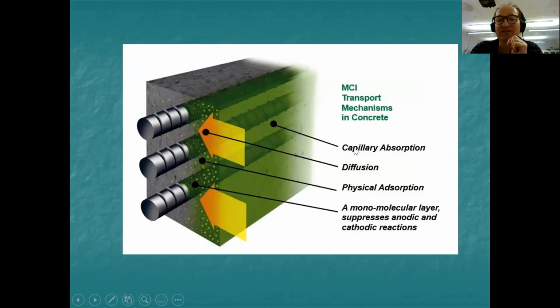And here it shows you again. So the first thing we have is capillary absorption. So you have to remember the concrete is porous. The corrosion inhibitor goes through the pores by a process of diffusion. And when it reaches the metal, it absorbs physically onto the surface of the metal, forming a monomolecular layer on the surface of the metal. And it suppresses the anodic and the cathodic reactions. It suppresses both of them. So this is a very powerful way of protecting steel in a concrete structure.